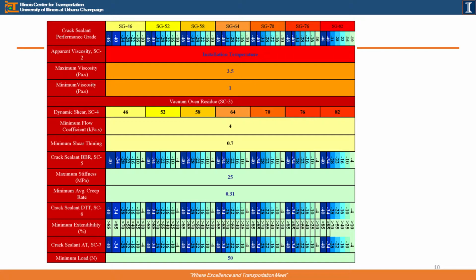However, silicone is not asphalt binder, so they had to modify the test procedure and the grading system and threshold, as you can see from here. Again, you can find all this in the AASHTO publication. Since everybody has limited time, with the given 30 minutes, I will not go into too much detail, but it's very much similar to the PG grading system here. Okay? So at the top, that's the high temperature grading system, and then the bottom, the second row, will be the low temperature grading system.